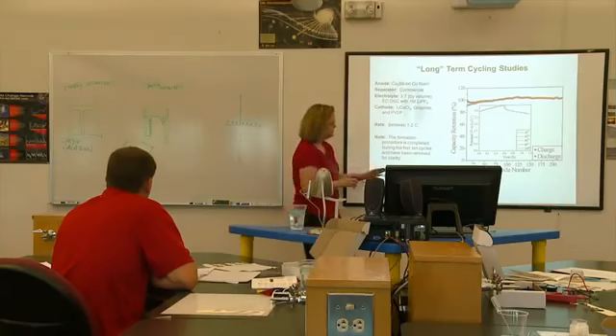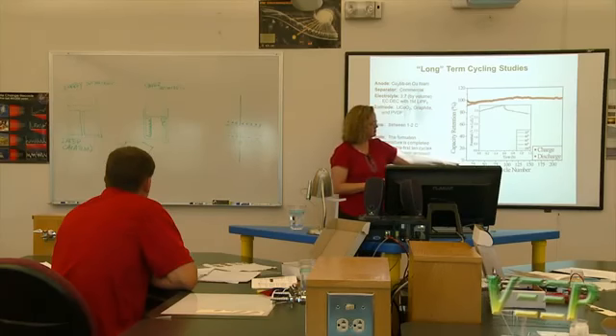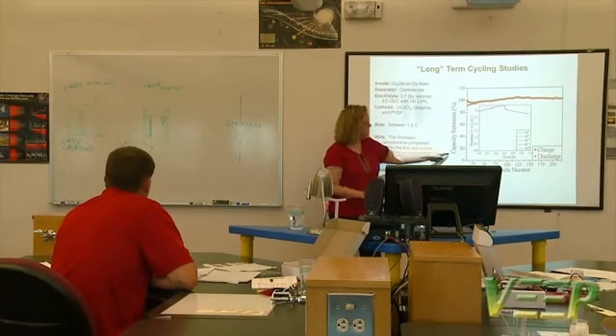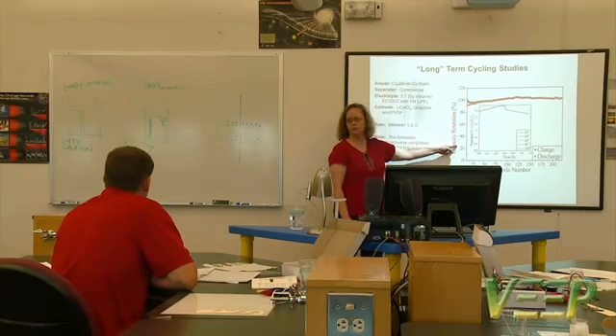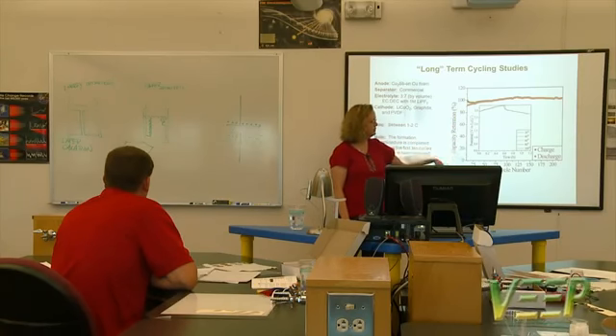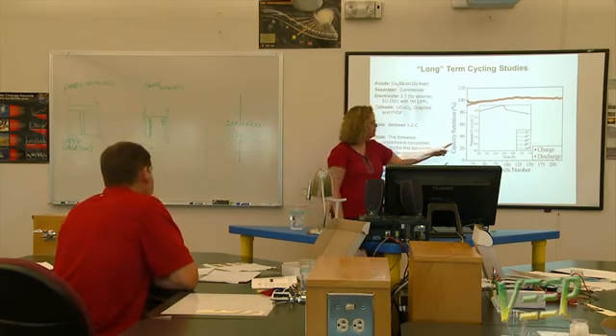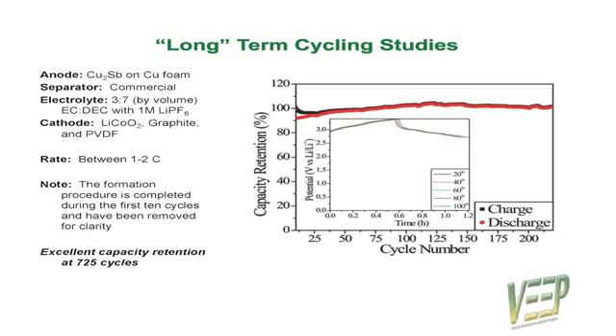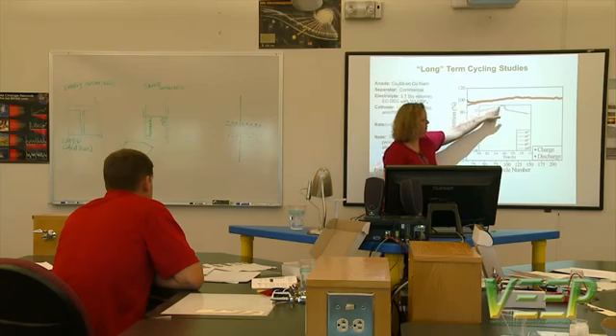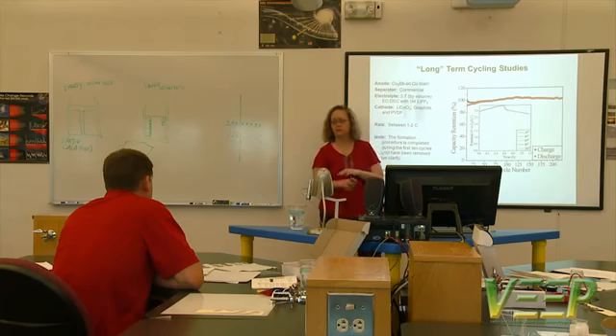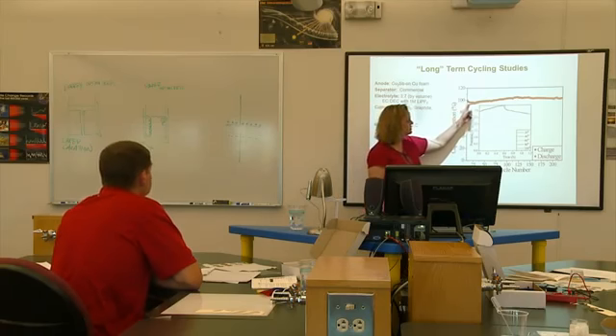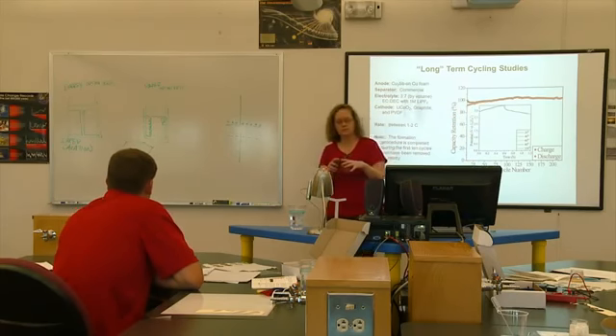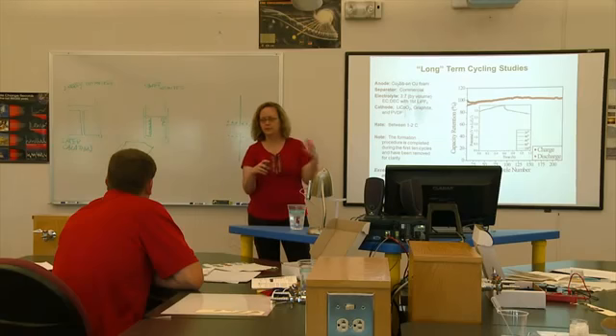What's important here is that if we go out to, in this plot I'm showing you, about 220 cycles, this is the percentage of capacity retained from where we started. There's a whole forming process I'm not going to talk about, but what's important is that if we look at voltage versus lithium metal as a function of time, every 20 cycles it doesn't change. All you need to get is that all these lines are the same. That to us is telling us our material's not degrading. It's acting exactly as it should. If we plot capacity retention, you see it's getting better over time. That's because we are roughening it every time it expands and contracts. And the rougher it gets, the more surface area it makes.